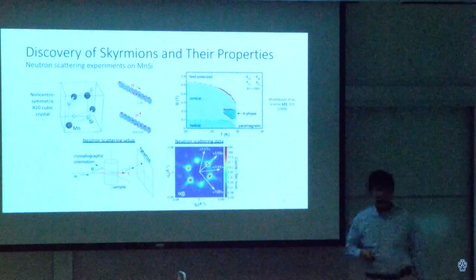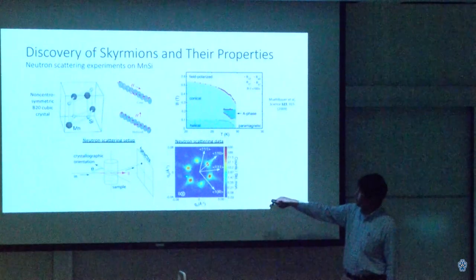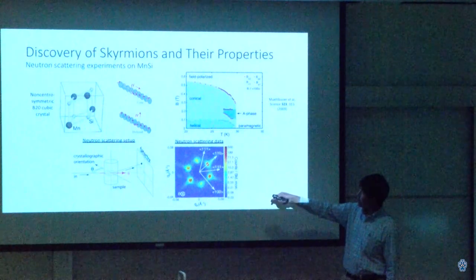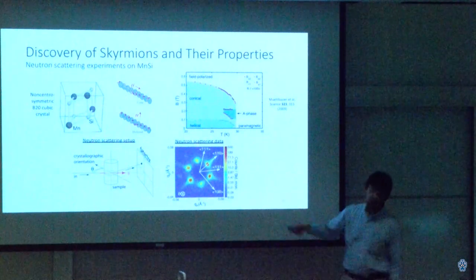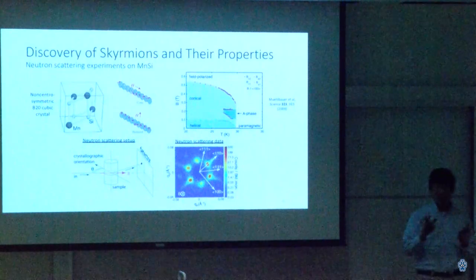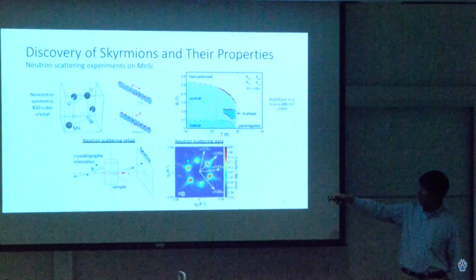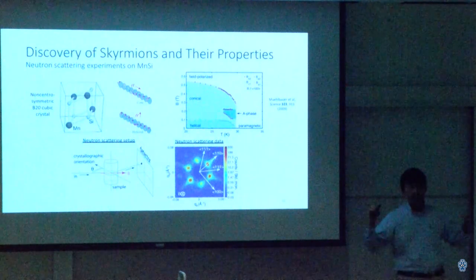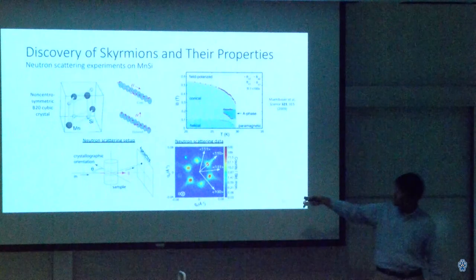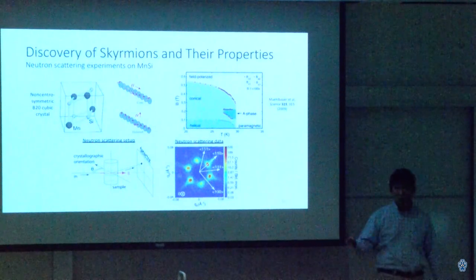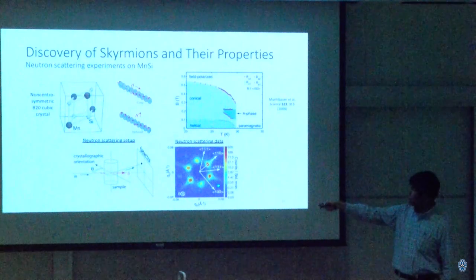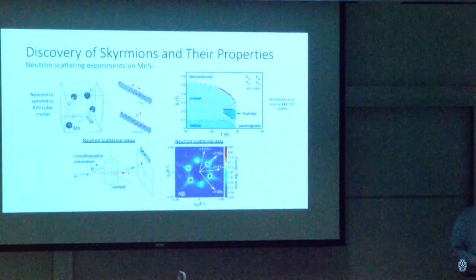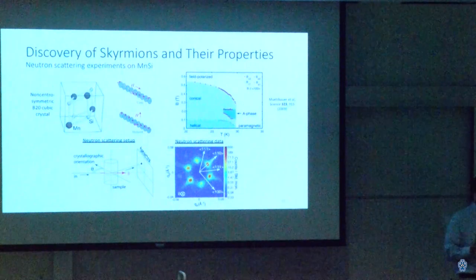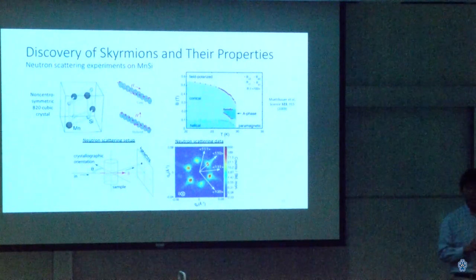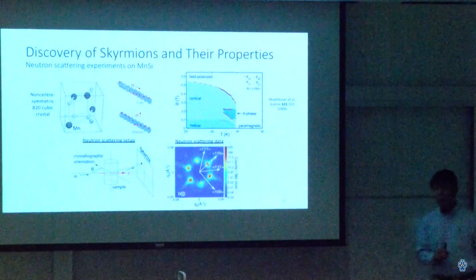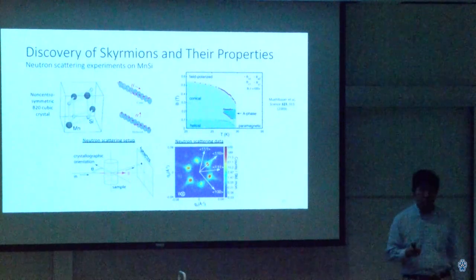If you know about Fourier transforms, here's also something else. You notice these blobs in between these main peaks? Well, they weren't there before. The diffraction pattern changed. It has six peaks shifted in direction, and it has so-called higher order peaks located here, here, and if they waited long enough to count enough neutrons, it would appear in every location that I'm indicating. That's a sign that the magnetic texture changed from that of a conical phase to something else, which they suspected was from a skyrmion state.